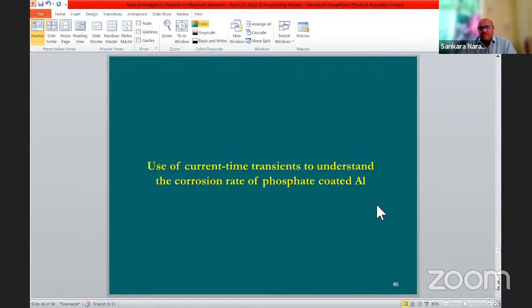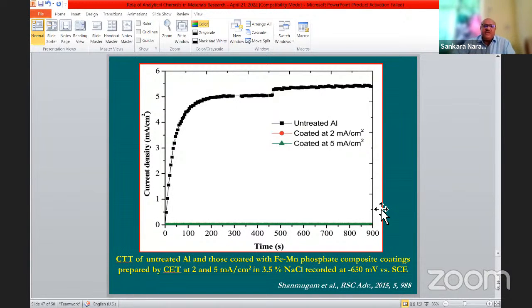Current time transient is one of the electrochemical methods normally used to follow corrosion. It is simply a measure of the change in current as a function of time, called the current time transient. So how can it be used to understand the corrosion behavior of phosphate coated aluminium? That's what we did. We followed the change in current as a function of time. We immersed the uncoated as well as coated samples in 3.5% sodium chloride solution, and applied a potential of minus 650 millivolts versus the saturated calomel electrode, and then measured the change in current as a function of time.